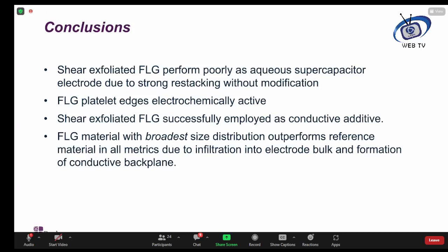We've shown that we can use shear exfoliated few layer graphene as a conductive additive, but we found, rather contrary to what we originally expected, that few layer graphene material with the broadest size distribution works best and outperforms a reference material which is constructed using a standard carbon black as an additive. And we think this is due to the infiltration of the few layer graphene into the electrode bulk, and in particular that this is somehow self-limiting, and the formation of a conductive backplane.